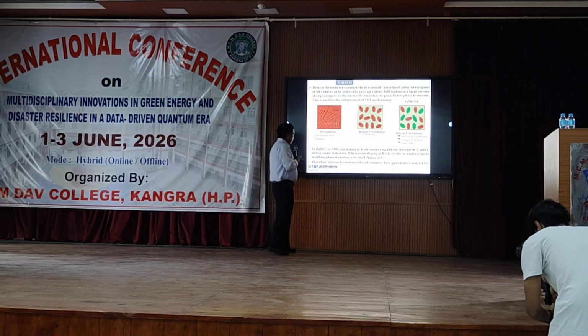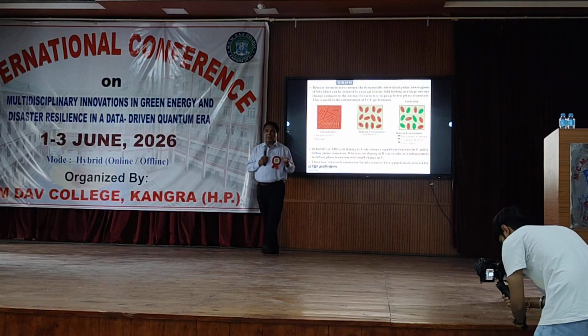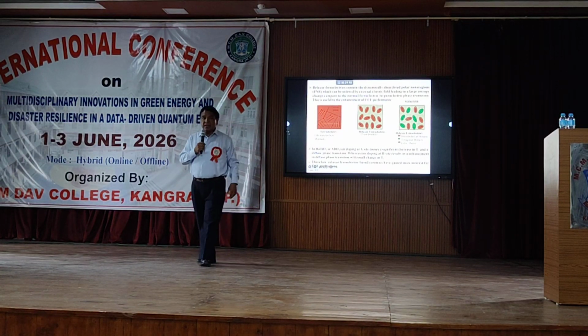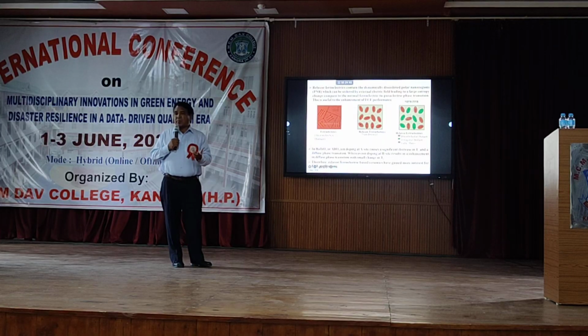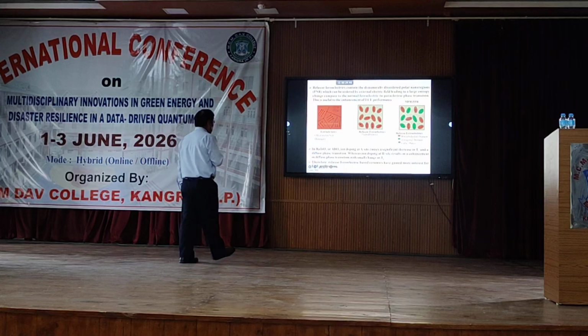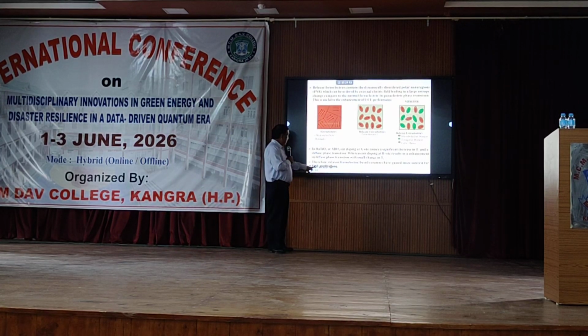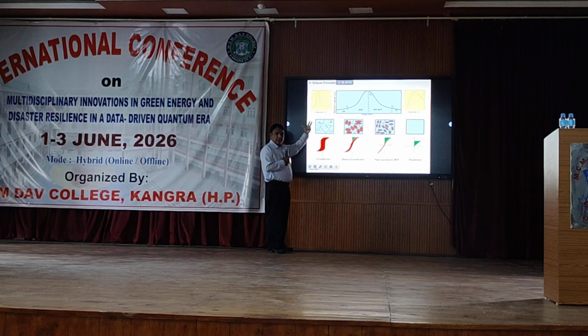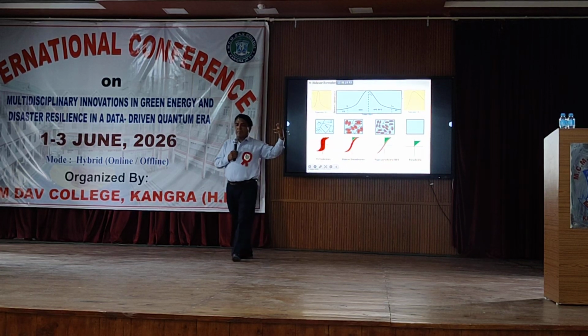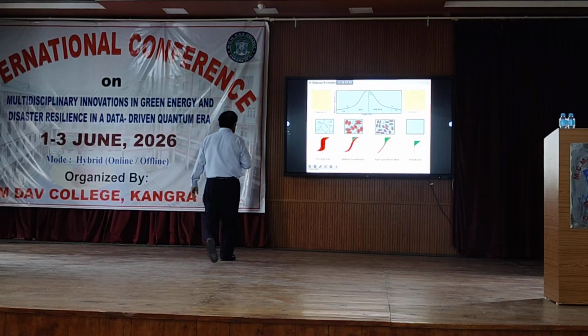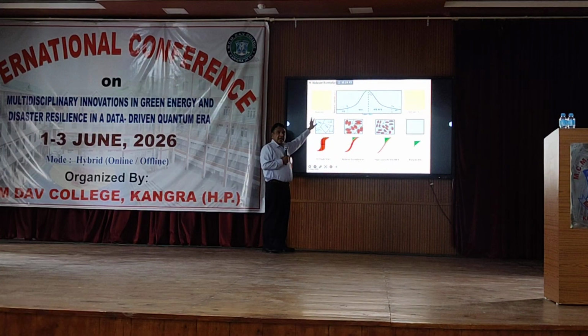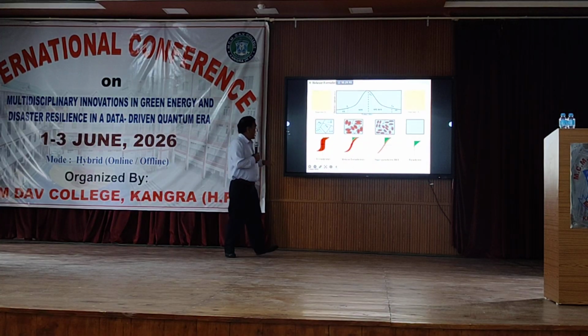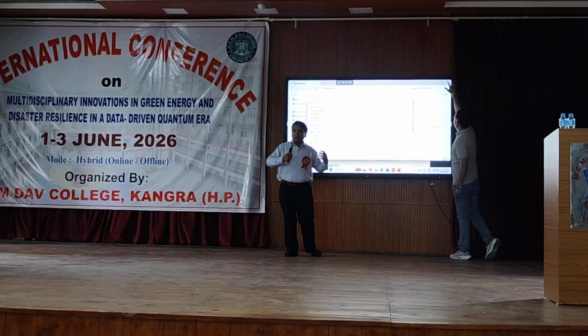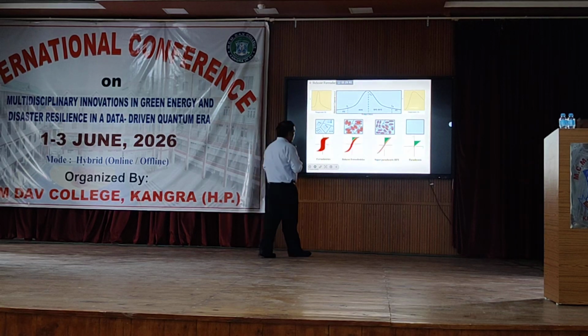And secondly, this barium titanate can be made having morphotropic phase boundary just by making substitution on the A and B side. So objective is to create the morphotropic phase boundary, and second is to bring the Curie temperature near the room temperature to enhance the electrocaloric effect. So this one again an illustration in the diagrammatical form, so as to have convincing interpretation of what I have said. So if you see the top, this left hand side, this is ideal ferroelectric having sharp peaks near the Tc, resulting in very severe hysteresis loop, and is very promising for memory devices. But for electrocaloric effect and energy storage, we require a kind of a broader peak, so as to have the temperature stability of the electrocaloric effect, along with slim hysteresis.